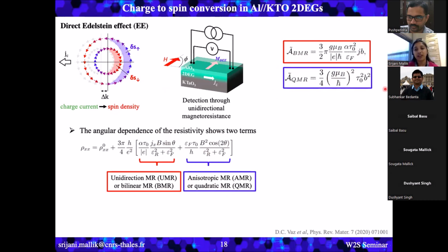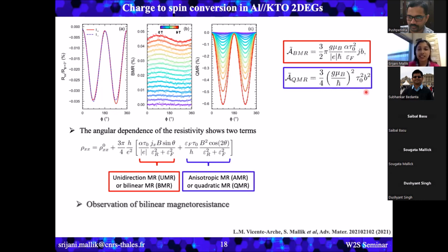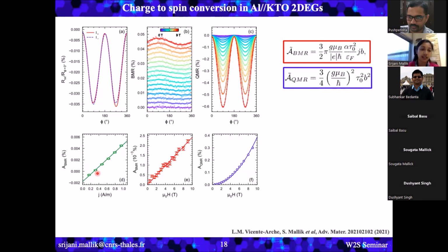So we did this measurement on our sample, and we found that for BMR, it really varies as sin theta, and for QMR, it varies as cos 2 theta. And the coefficient of BMR varies linearly with current density as well as magnetic field. And the coefficient of QMR varies quadratically with magnetic field. So far, so good. And here you can see that in the coefficient of BMR, there is the Rashba coefficient.